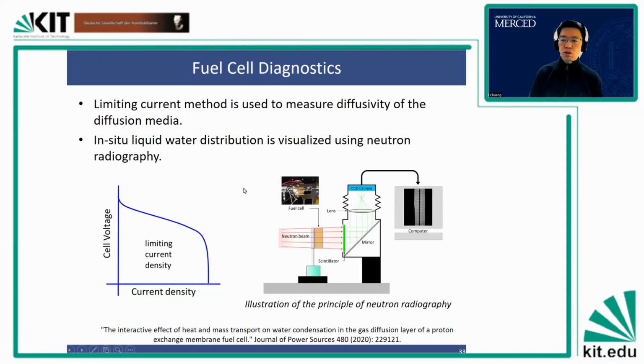And then we also continue to use in situ water distribution study through neutron radiography. As you can see on the right here, the resolution of the neutron radiography continues to improve. So now instead of seeing water inside the channel, which was my study at Penn State University, we are able to see liquid water inside very fine pores. Okay, the resolution is down to about 5 micron scale. Okay, so now we can do a little bit more with this tool.